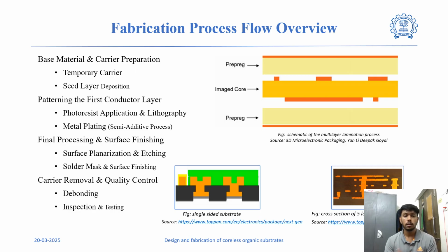The electroless copper plating is used to create a thin conductive layer inside the via and the surface of the substrate. These processes rely on chemical reaction to deposit the copper. These seed layers provide the conductive base for the subsequent electroplating, which ensures the uniform copper coverage inside the via and surface traces. Which also improves the adhesion between electroplated copper.